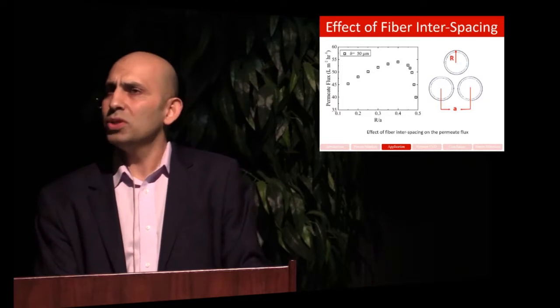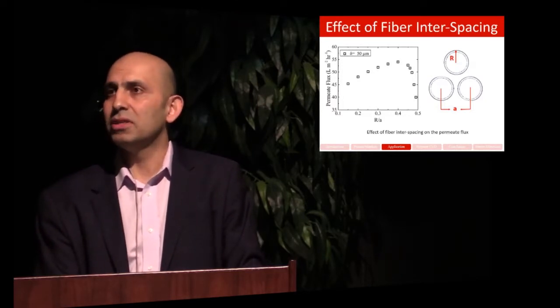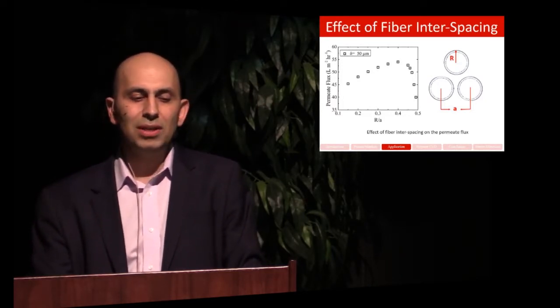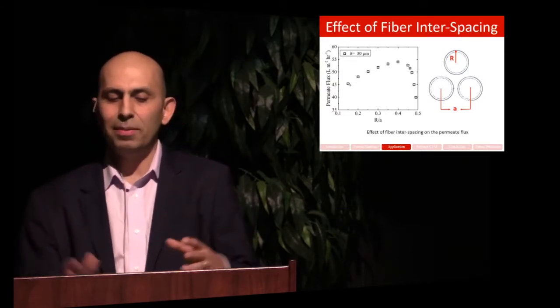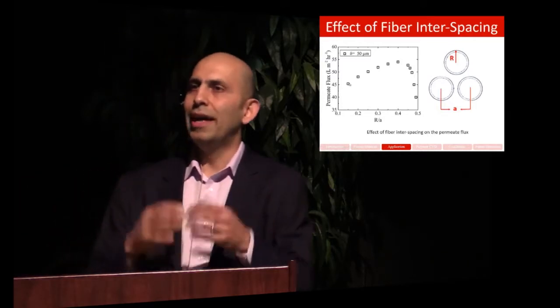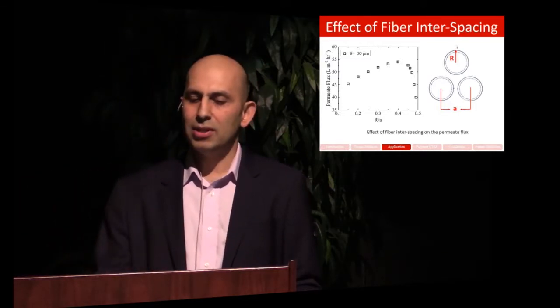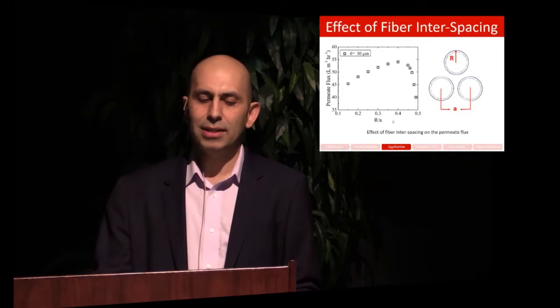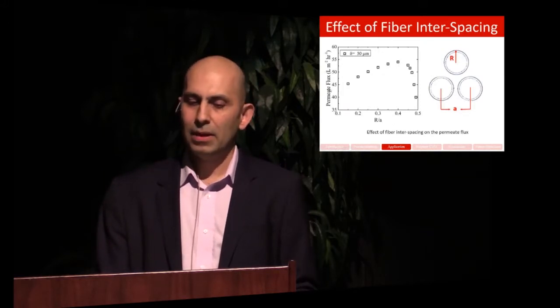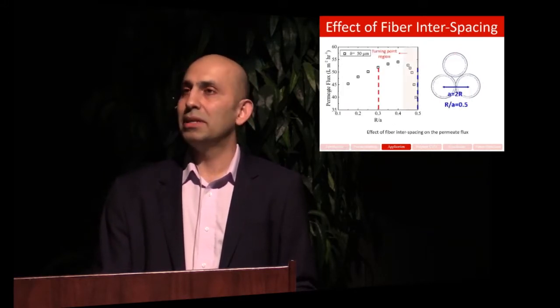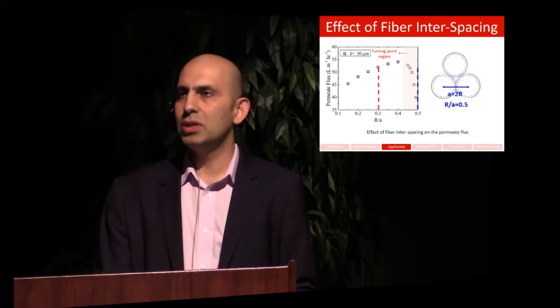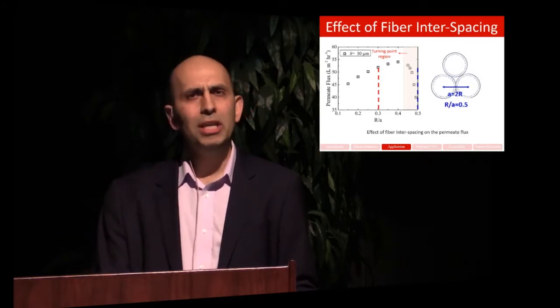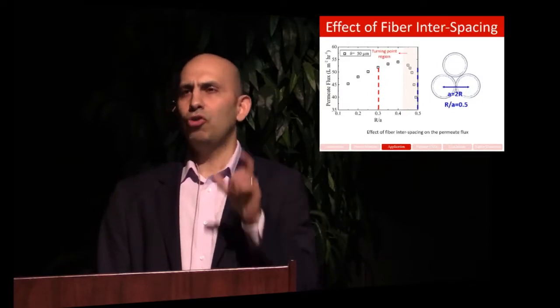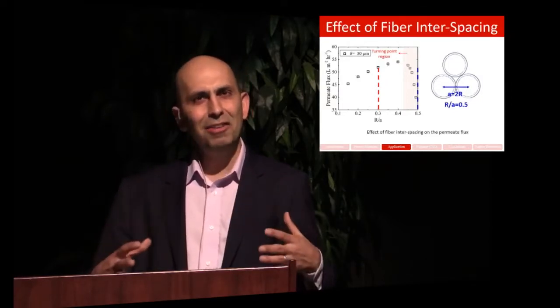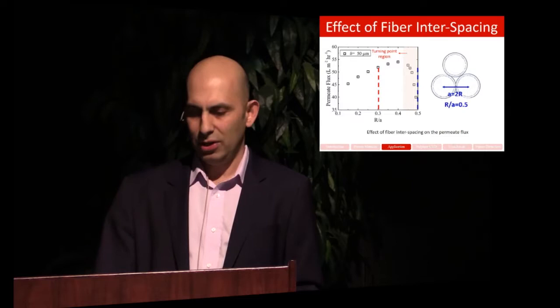And it turns out the most interesting one is the spacing of these fibers, because we do see some sort of initial rise in the flux as these fibers are getting closer to each other, and then a sudden drop. Here's the R over A ratio on the axis, and here's the permeate flux. So when they're coming very close to each other, we're losing a significant amount of flux. So we need thin membranes, the right length, exactly well separated in the right configuration.